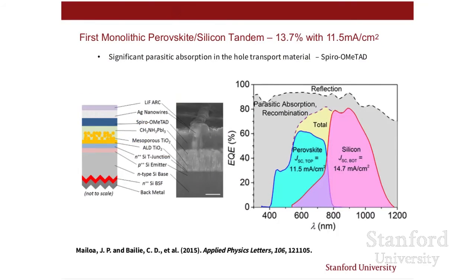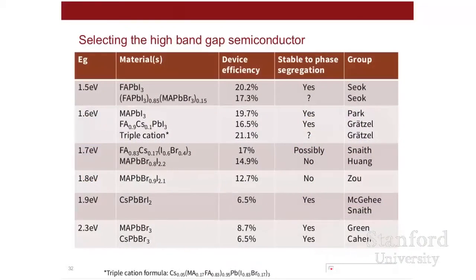My group was also the first to demonstrate a two-terminal tandem in partnership with Tonio Buonassisi at MIT. They made a silicon cell with a tunnel junction on top, and then we put a perovskite cell on top of it. And here we got 13.7%, and we identified we were having a big problem with our hole transport layer absorbing photons, which we didn't want it to do. But a lot of progress has been made on that as well.